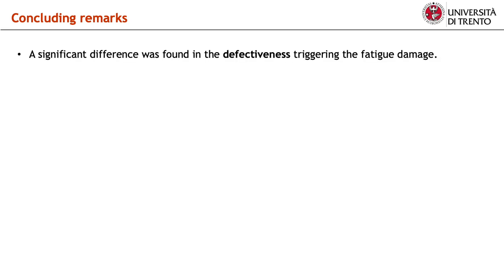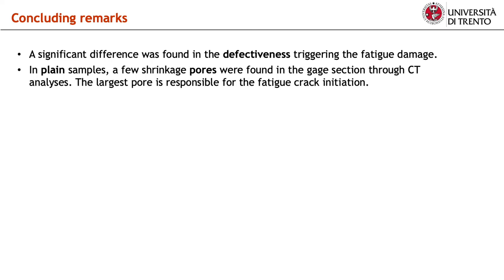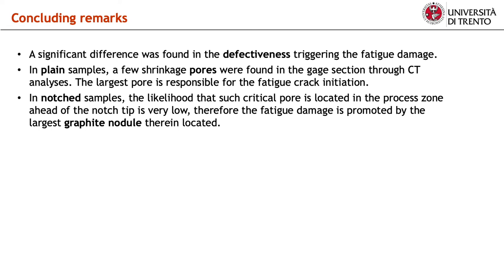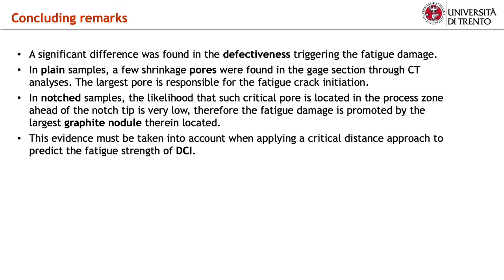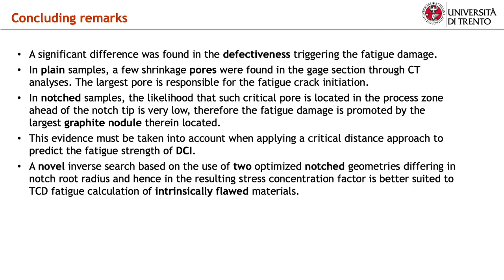Now, I'd like to summarize the main points of this work. A significant difference was found in the defectiveness triggering the fatigue damage. In plain samples, a few shrinkage pores were found in the gauge section through CT analysis. The largest pore is responsible for the fatigue crack initiation. In notch samples, the likelihood that such a critical pore is located in the process zone ahead of the notch tip is very low. Therefore, the fatigue damage is promoted by the largest graphite nodule therein located. This evidence must be taken into account when applying a critical distance approach to predict the fatigue strength of ductile cast iron.